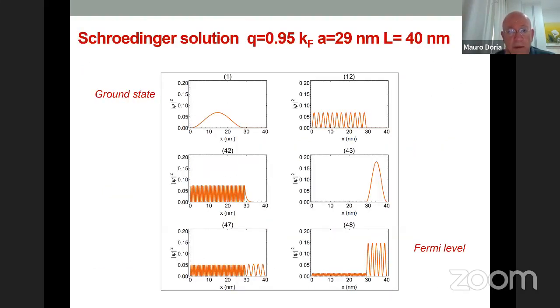And so we go to the Schrödinger equation. Look at here, I have a thickness, which is the size of nickel bismuth. I have a total thickness, and I have a parameter that tells me how high this barrier is near the Fermi surface.